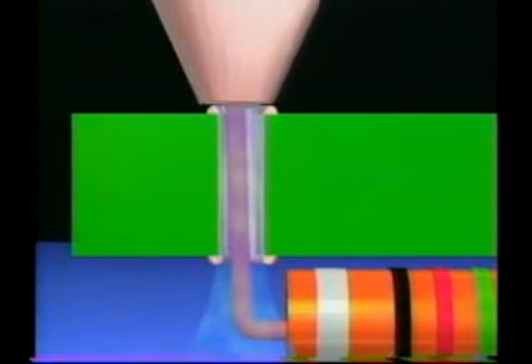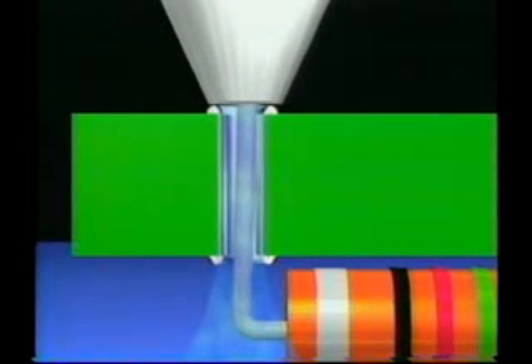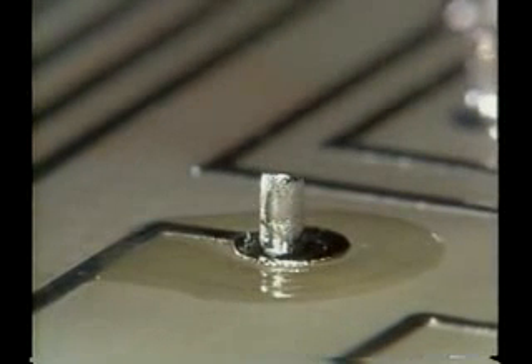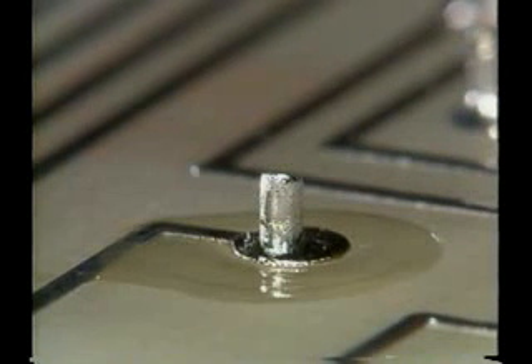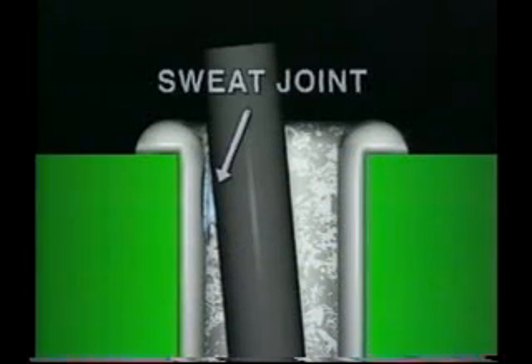The fast-moving air will now cool the metals inside the hole. This will also make sure that the liquid solder is drawn all the way into the vacuum chamber rather than stopping inside the tip. After 1 or 2 seconds, you can remove the tip, then stop the vacuum. The component lead will probably lean back against the edge of the hole wall. There may be a few small beads of residual solder inside the hole. If we didn't cool this residual solder with fast-moving air, the lead could now reattach itself to the side of the hole. This is called a sweat joint.